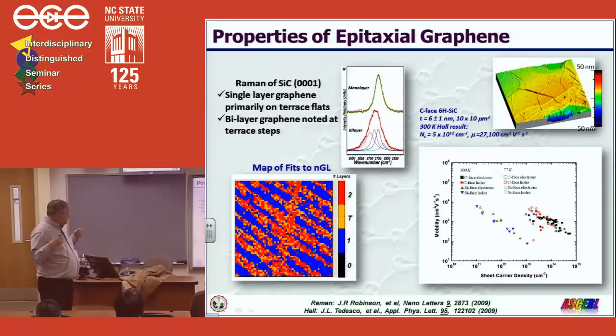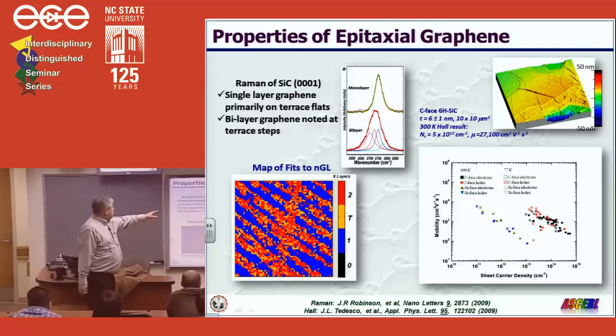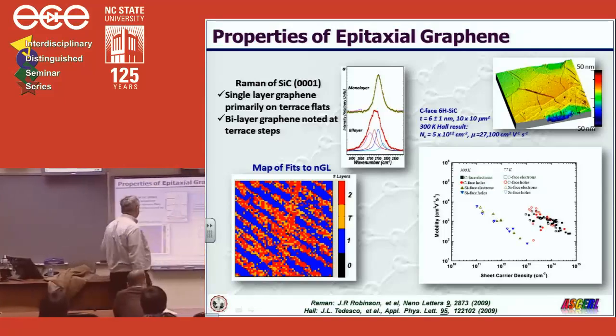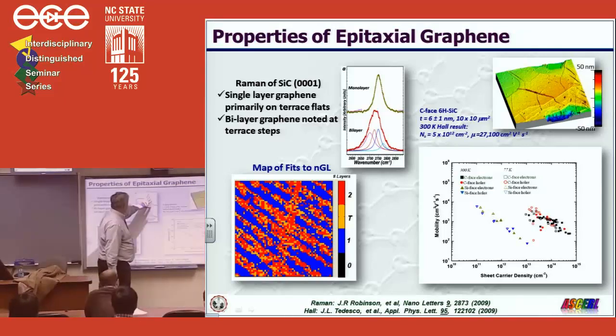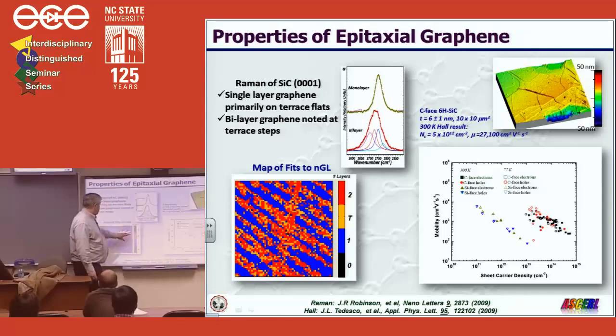Now, we use Raman spectroscopy as another probe, and in this particular case, we can use it to determine the number of layers of graphene. A single layer of graphene gives a symmetric spectrum consisting of one Gaussian, whereas bilayer graphene gives a composition of 4 Gaussians summed together in the Raman spectrum. Using this approach, we mapped out a square, about 50 by 50 microns, and we mapped out the number of layers.